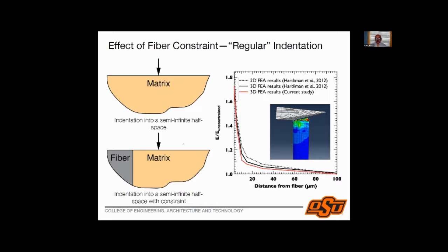So we started with the finite element solution of looking at the elastic modulus divided by the unconstrained elastic modulus as a function of distance from the fiber. As I come closer and closer to the fiber, my modulus goes up. These FEM solutions assume that the material doesn't change, so the increase in modulus that you get is only because of the constraint effect. And this is how the indentation process looks. We have modeled both 2D and 3D indentation, and we have also compared ourselves with results in the past. So that tells us what's going on. But now we know that the constraint effect is real.